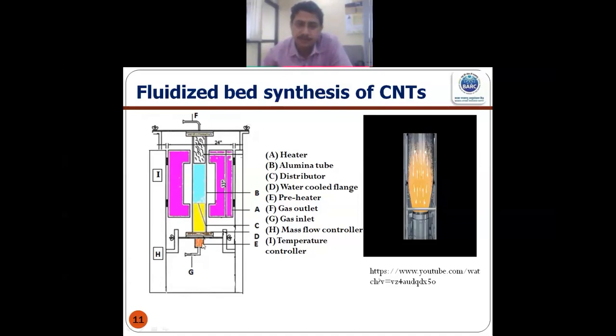and once fluidization starts, then we'll send the precursor from the preheater, which is here where my precursor is. From here the ferrocene is kept, and ferrocene is passed along with the carrier gas. It gets cracked and deposits, iron nanoparticles get deposited on the carbon black, and then acetylene is sent. On cracking at high temperature, acetylene gives carbon and hydrogen, and there are mechanisms by which the carbon is adsorbed onto the iron nanoparticle, and finally it comes out in the form of nanotube. I'll discuss that in subsequent slides.